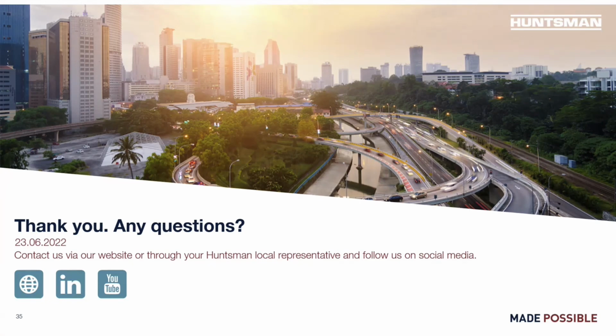So Araldite PZ 3961 is not really a product to be used in the construction area. It's a solid epoxy resin dispersed in water. So it's a very special product which is generally used for anti-corrosion coating in combination indeed with 3986. The adhesion is very good on metal and for some flexibility reason. In construction, it doesn't come to me as the first choice because you will have still a solid material.